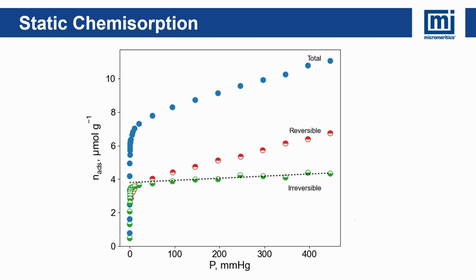Once the first isotherm is collected, a vacuum is applied to remove any weakly bound CO physisorption. The process is then repeated to obtain the second isotherm, since CO chemisorption is more difficult to remove. The second isotherm will primarily reflect the CO physisorption. By subtracting the second isotherm from the first at each pressure point, we can isolate the volume of CO chemisorption.